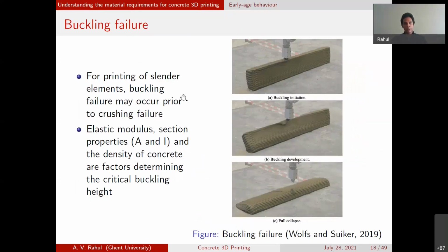The other type of failure, especially associated with slender elements, if you make very thin, architecturally appealing elements, is a failure from geometrical instability, such as a self-buckling failure. You can see here, as the structure is being built up, a lateral instability occurs in the material, and the material fails by buckling. As you would have learned in your strength of materials course, when you look at equations that assess the critical buckling load, it involves the material parameter elastic modulus. So it's not the strength of the material, it's the elastic modulus that dictates the tendency of the material to buckle. So you require two parameters essentially to decide if the material would cause print failure or not.